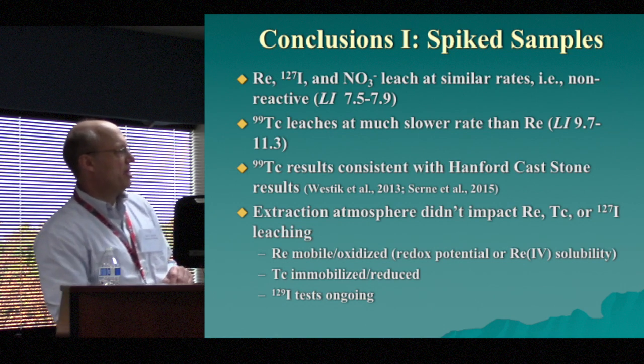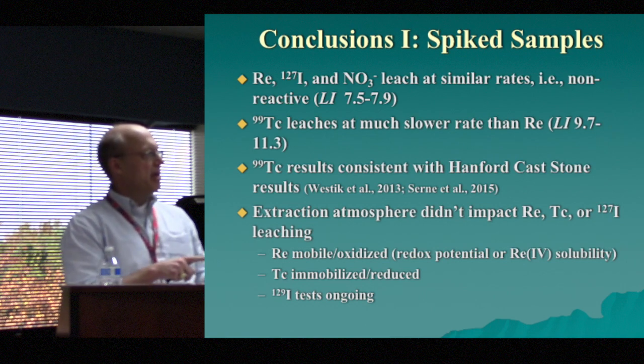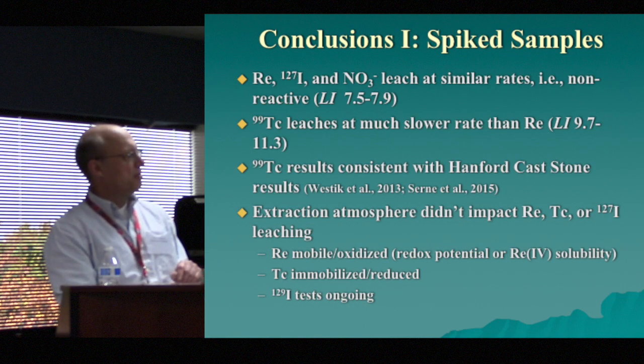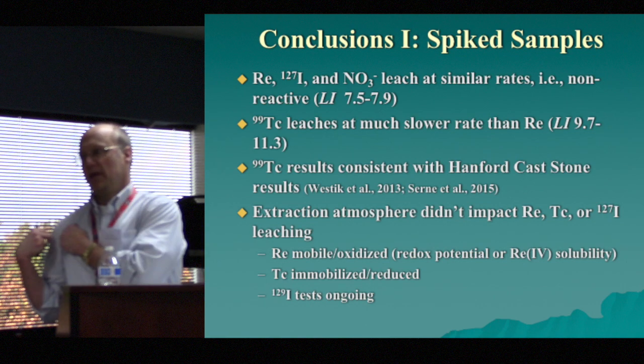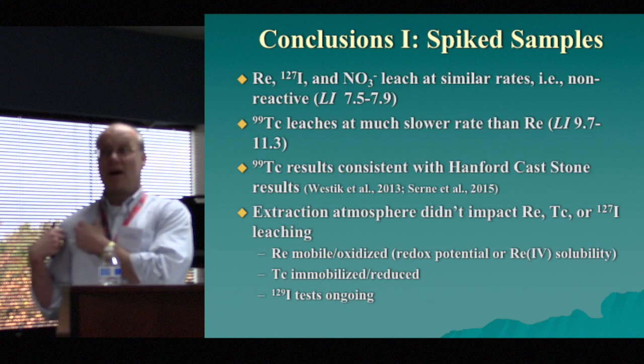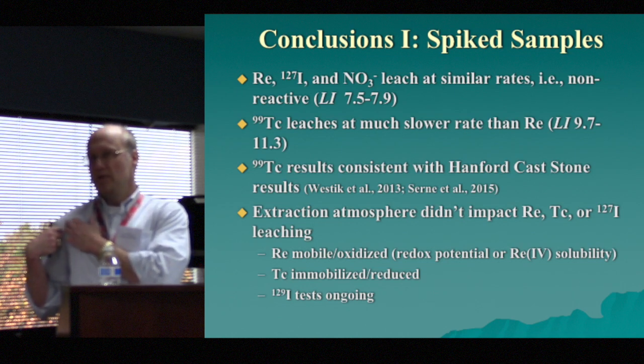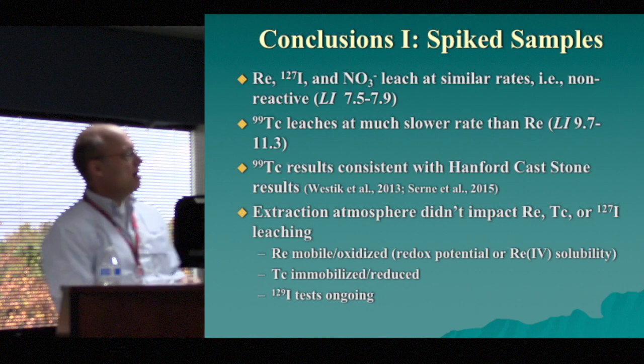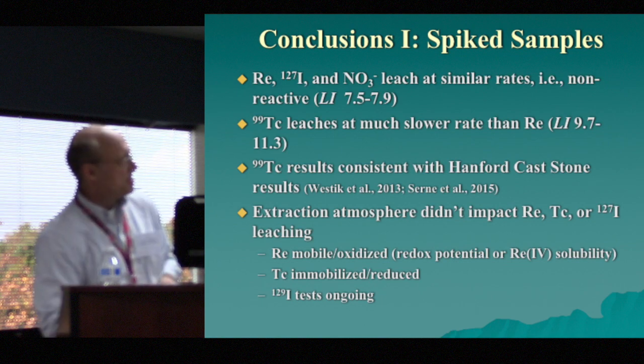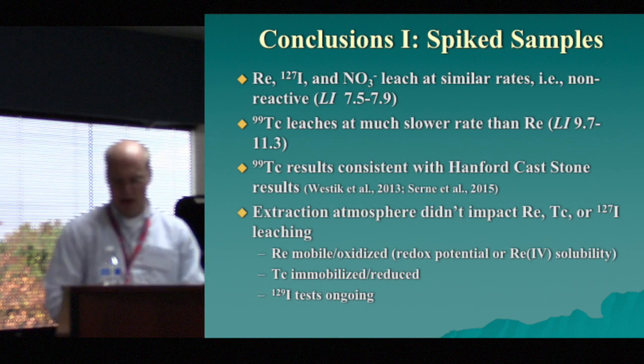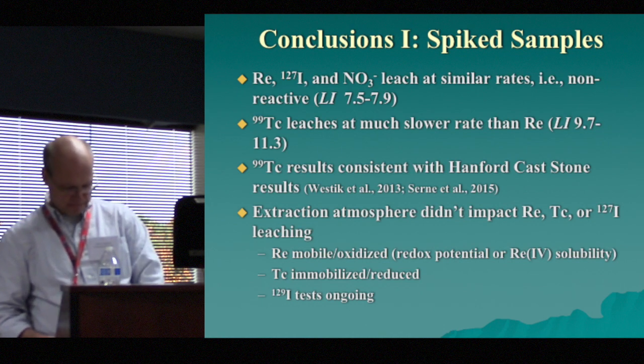The other possibility is it's actually hard to get some very reliable data on rhenium, but rhenium solubility can be orders of magnitude potentially higher than technetium in these oxide phases. And we also have ongoing tests with iodine-129 in the SCU cores.